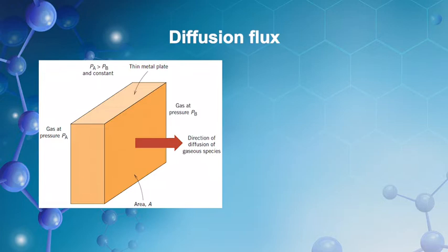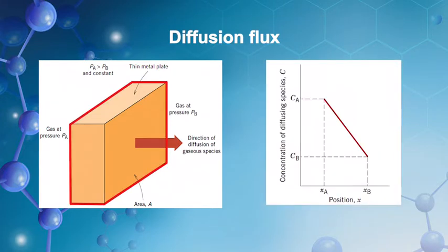If you want to measure the diffusion flux empirically, then you need to do an experiment. You have to make a thin film or membrane of known cross-sectional area. You have to impose the known concentration gradient, and finally measure how fast atoms or molecules diffuse through the membrane. One of the typical situations is shown in this figure.